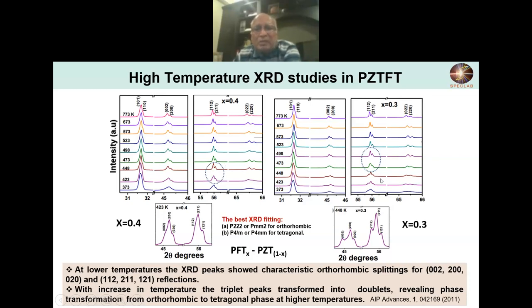Similar behavior was seen. This is for x equal to 0.4, and for x equal to 0.3 we also saw similar behavior. The triplet becomes the doublet as you go to higher temperatures. We analyzed the data further, and we found that the orthorhombic phase was indeed either P222 or Pmm2, and the tetragonal phase was P4bm or P4mm.